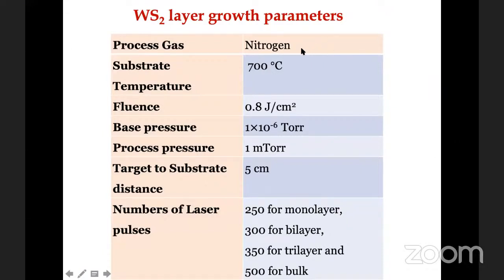So to grow the WS2, we use a nitrogen ambient and similar processing conditions as we discussed in the previous case. The only difference is that the number of shots optimized for monolayer, bilayer, tri-layer, and bulk are going to be more, because in the previous case, in the MoS2, we used only 50 shots. In this case, it is 250 shots and 300 shots.